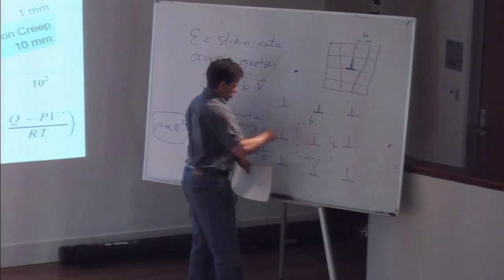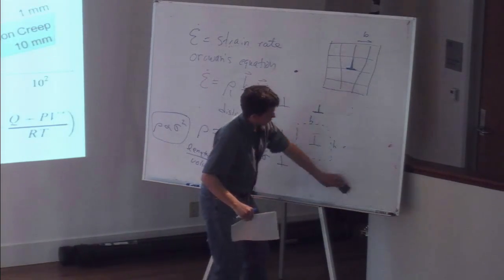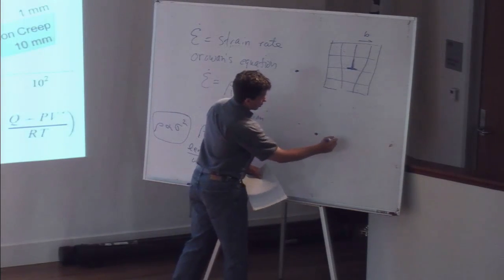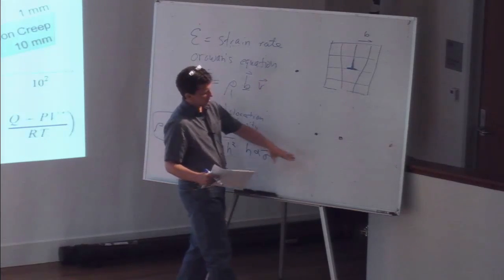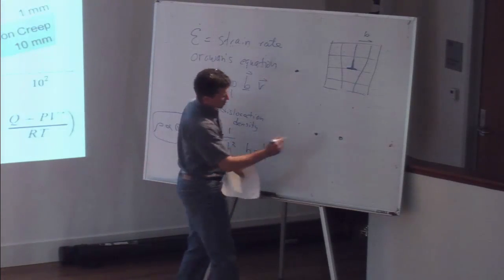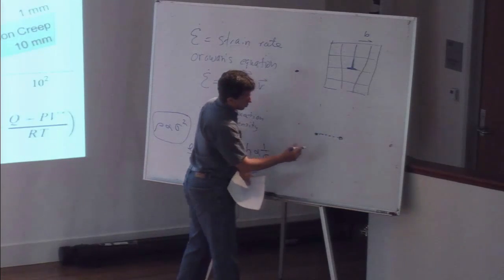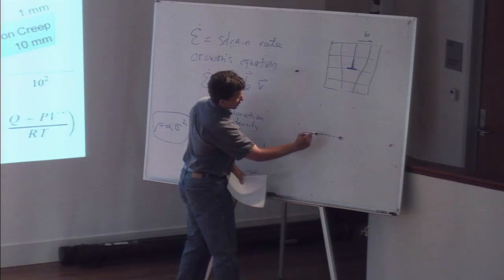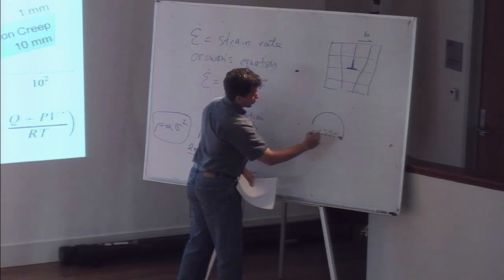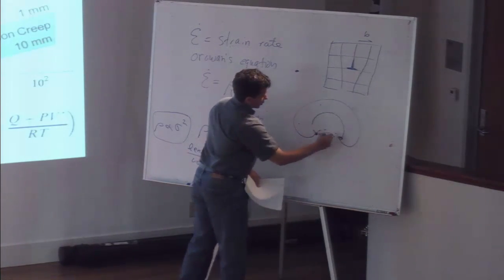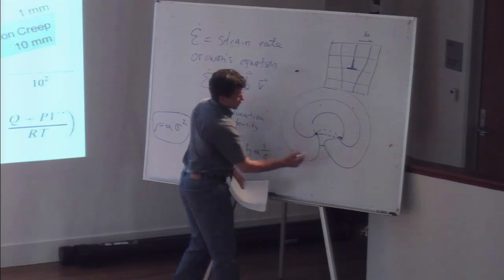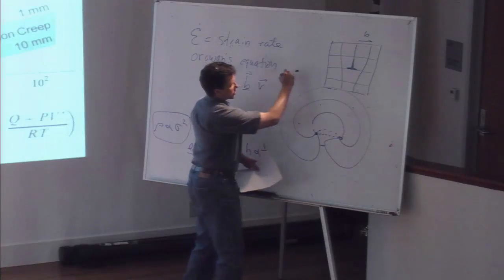Maybe some of you have seen cartoons of this. So this is two dislocations coming out at you, and they're stuck. And there's a little line in between them. And if you apply a shear stress like this, this line will start bowing out. So this is a sequence with time. And then eventually it will kiss. And after it kisses, it creates